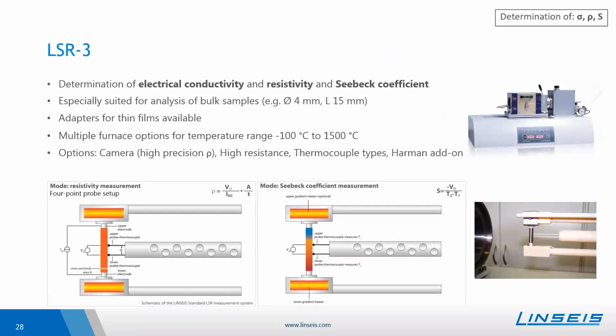The first instrument here is the LSR3. It allows the determination of the conductivity, resistivity, and the Seebeck coefficient of many materials. It is especially suited for the analysis of bulk samples. So typical sample sizes are bars with a diameter of 4 millimeter and a length of 15 millimeter. However, there are also some adapters for thin films. So either thin flexible films or thin films on a substrate.